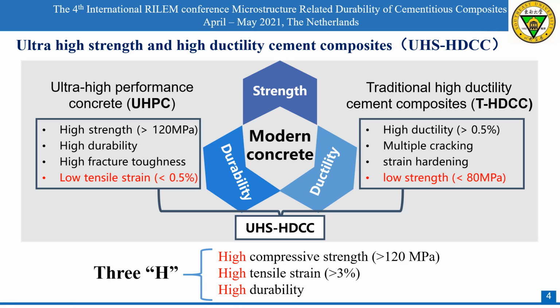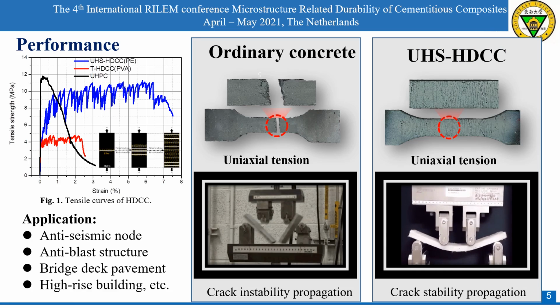Based on these two materials, UHS-HDCC is developed. It refers to a special fiber-reinforced cementitious composites with compressive strength greater than 120 MPa, tensile strain capacity greater than 3%, and shows strain hardening behavior and multiple cracking characteristics. The excellent performance of UHS-HDCC gives it better potential when it is used to resist high vibration in buildings. UHS-HDCC is mainly used in antiseismic nodes, anti-blast structures, bridge deck pavement, and high-rise buildings.